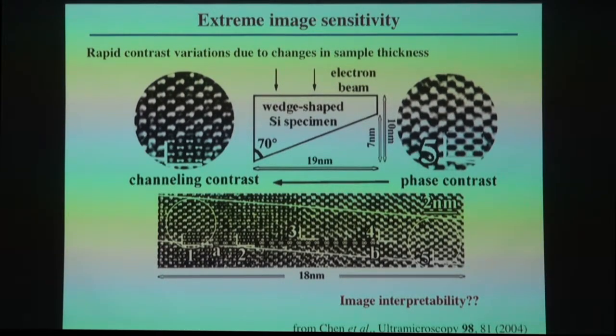One of the hidden, ugly little secrets that we sweep under the carpet is that once you improve resolution, you have extreme image sensitivity. Very nicely shown by Chen and colleagues, they took a wedge-shaped silicon sample. It's only 3 nanometers thick at this position, and here it is 10 nanometers thick. Here is the experimental image, and here are image simulations. You'd say, okay, at 3 nanometers thick, I can certainly just resolve the silicon dumbbells. And here we are in a channeling contrast mode. The sample is 10 nanometers thick, and the image simulation matches nicely with the experiment, given a bit of noise.